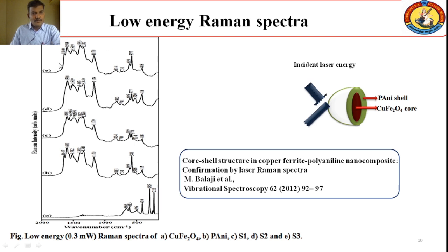Similarly, S3 also, but here there is no characteristic behavior of spinel cubic ferrite element exactly at 295 centimeter minus 1. There is no maximum intense characteristic peak of this copper ferrite which is present in S1, S2 and S3. So from that we can conclude it gives the exact behavior of only the shell element, that is not penetrated inside the core element, so it gives only the characteristic behavior of polyaniline shell, because here we are using very low energy, 0.3 milliwatt.